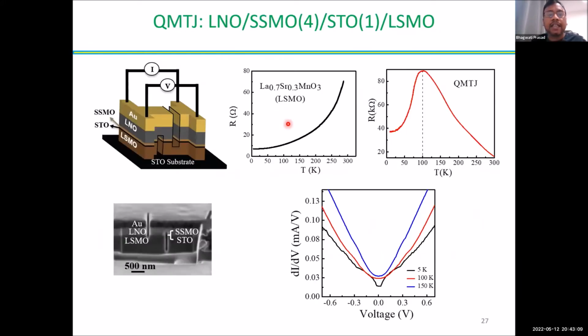In that case, I have used lanthanum strontium manganese oxide, LSMO, which is a ferromagnetic metal. This is R versus T of LSMO when you make a tunnel junction. Again, the lowering of the resistance at low temperature indicates that some spin filtering is happening. This is the dynamic conductance versus voltage curve, which is quasi-parabolic in nature. At low temperature, we see some sort of zero bias anomaly. That could be some kind of scattering happening at the interface.